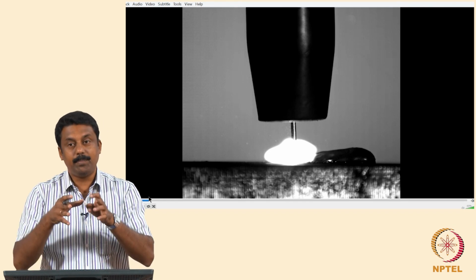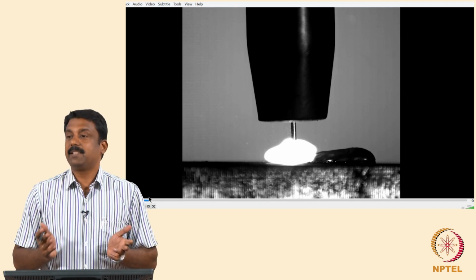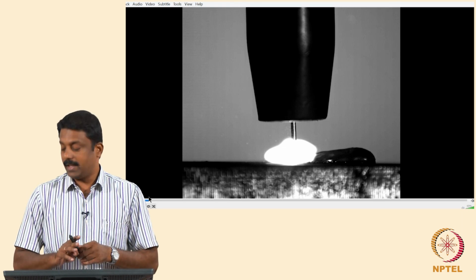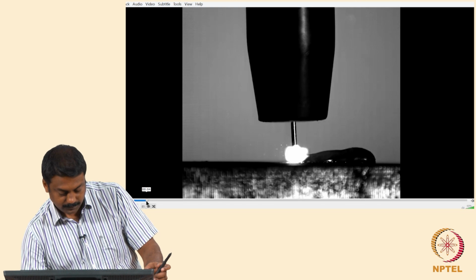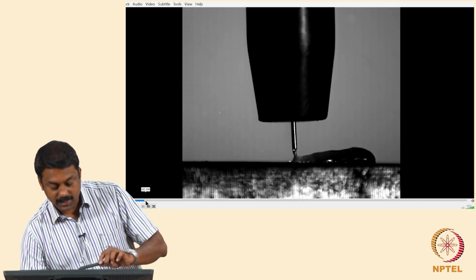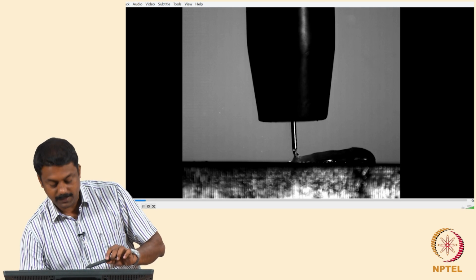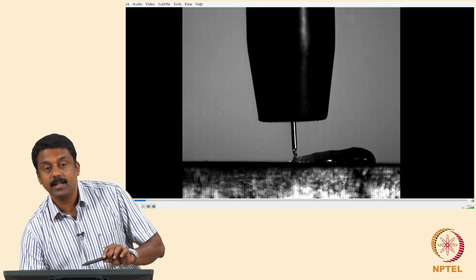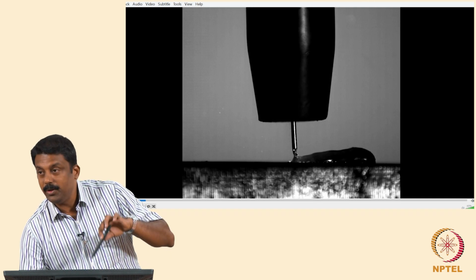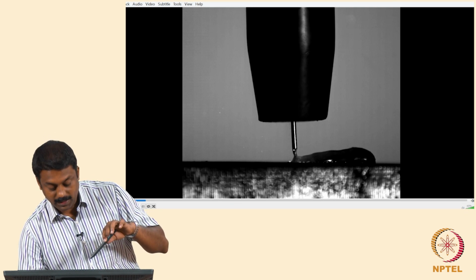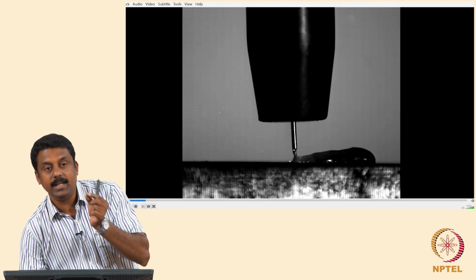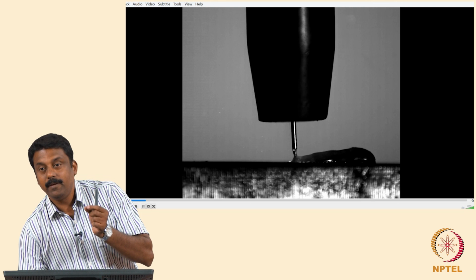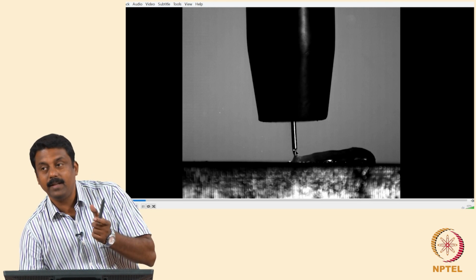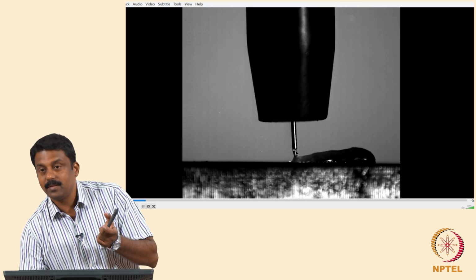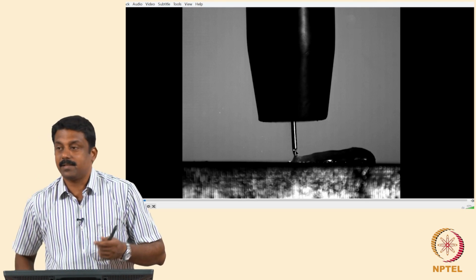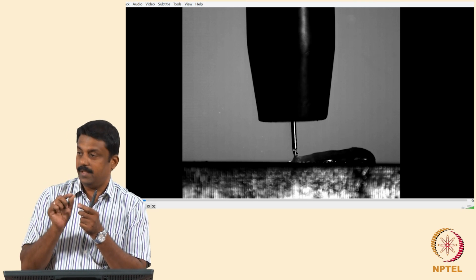Okay. So what happens if you keep on passing the current? So then you will have an explosion. Okay. So if the current is passed continuously, suppose an equal amount of current is passed like an arcing current, and you have a very small area neck forming when you are retracting or when you are doing a short circuiting, and you have an enormous amount of Lorentz force concentrating on a very tiny neck. Okay. So if Lorentz force is concentrating on a tiny neck, obviously it will cause an explosion, right, because if you keep the current constant, the amount of Lorentz force is confined to a very tiny area.